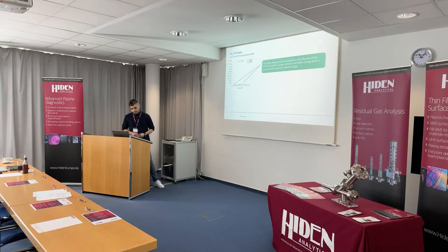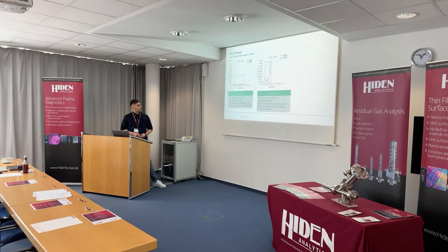Why do we see two peaks in our IDFs? The lower energy peak corresponds to the influence of the minimum sheath voltage, whereas the higher energy peak is caused by the maximum sheath voltage. And why do we see these differences in the width of the peaks? At lower frequency, the ion transit time is almost equal to the RF cycle, so we see more separated peaks. And at higher frequency, the ion transit time is much higher than the RF cycle, so the peaks are more unified, and ions respond to the average sheath potential.